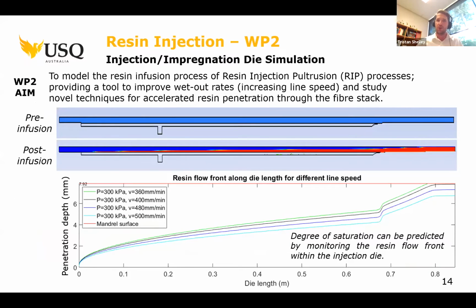Moving on to work package 2. So this is the infusion work package that we're looking at. So we're looking to model the resin injection pultrusion process, providing tools to improve the wet out rates, which in turn allows us to increase speed, and study novel techniques that may assist us in accelerating the penetration of the resin through the fiber stack.